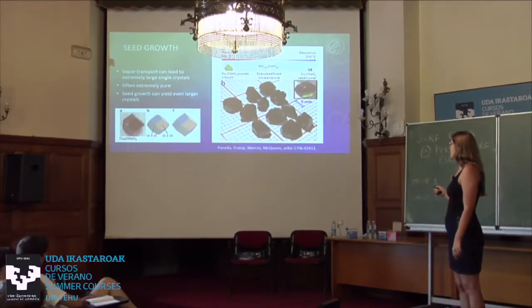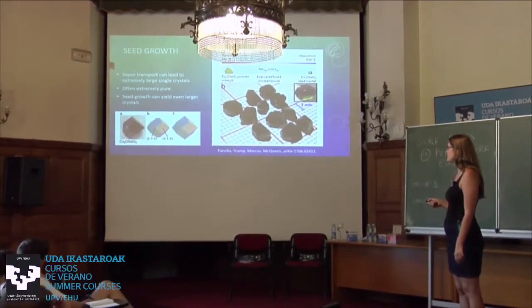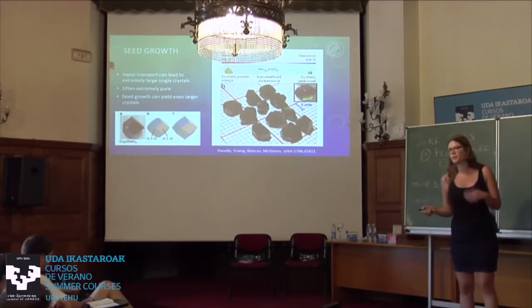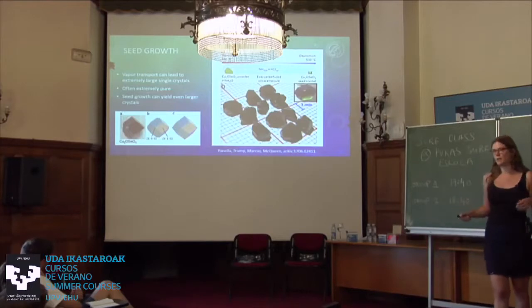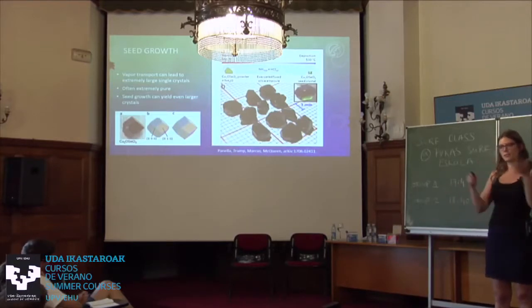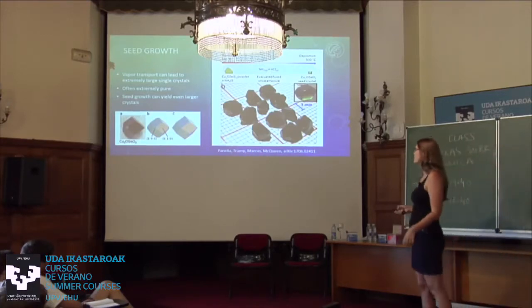And also what is nice if you use a seed is that you get fewer different crystal phases. So they showed that you get this 100 phase only at the places where the crystal is attached to the tube. And you get only the other phases, only the 110 phases of a crystal if you have a seed growth. So you have some methods even for designing which crystal phases you get. So there's lots of control you can actually have with careful growth methods.